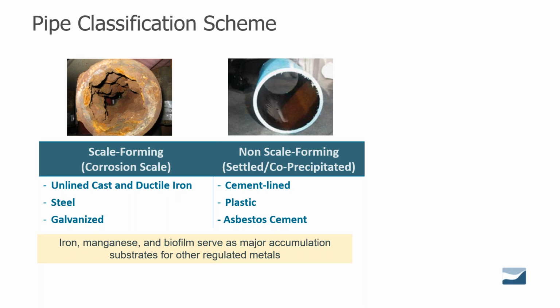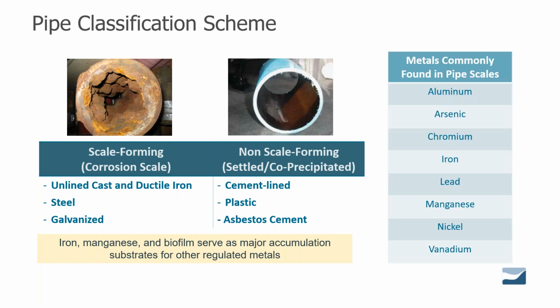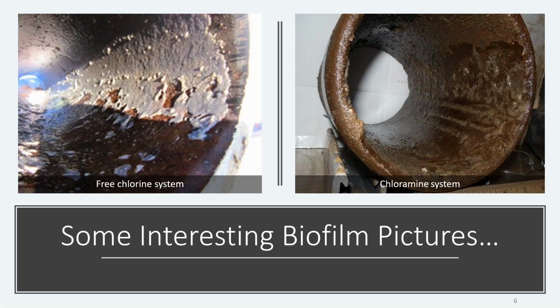The iron and manganese and biofilm that accumulate on these pipes serve as major accumulation substrates in and of themselves for other regulated metals. We commonly find these metals at varying concentrations in these pipe scales. And it's not just the big corrosion tubercles we worry about. Yes, there's a lot of iron and there's a lot of massive material, but these very thin films can be great accumulators for biofilm and these other regulated metals. When we talk about biofilm, here's the type of thing we see out there. We lovingly call these the bacon fat slides, what we can see in a free chlorine system and in a chloraminated system. So just to provide a visual for those that don't get to look inside the pipes as often as we do.